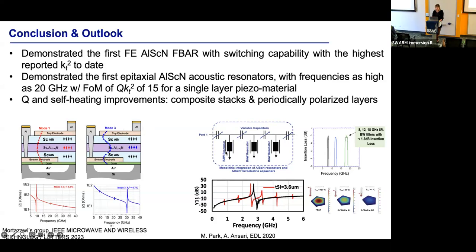And another way is using a thicker layer stack, such as silicon or silicon carbide, that can improve the quality factor of your resonator. It'll degrade the KT squared, but the Q times KT squared, the figure of merit, is what matters, right? So you can add more peaks by having a composite structure. This will help with the Q, it'll help with the self-heating, and it can enable multiple peaks that you can switch between for building switchable filters or covering a wider range of frequencies.